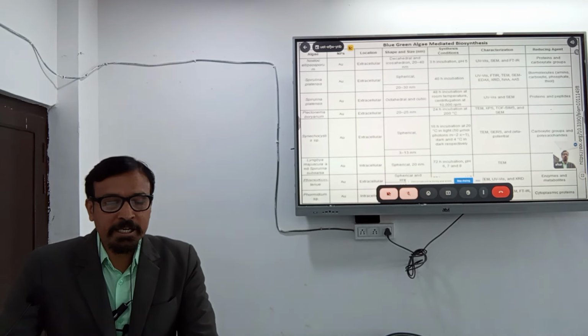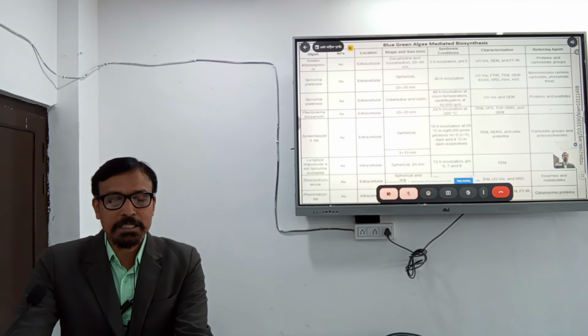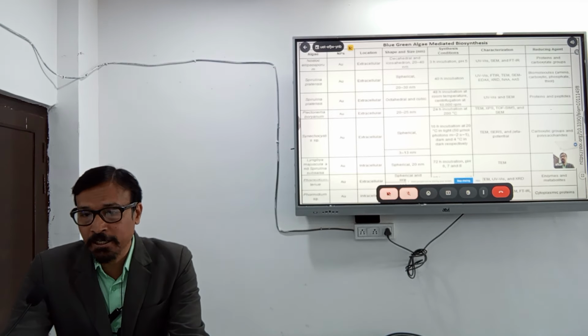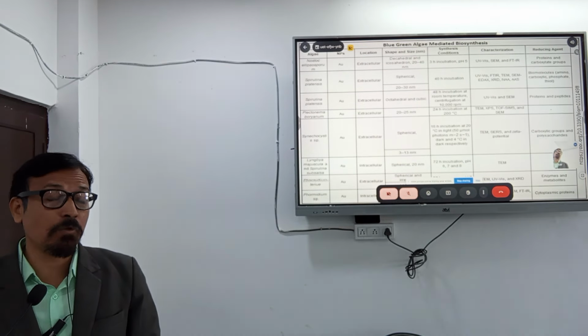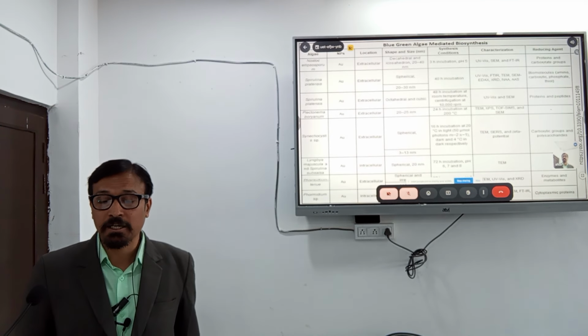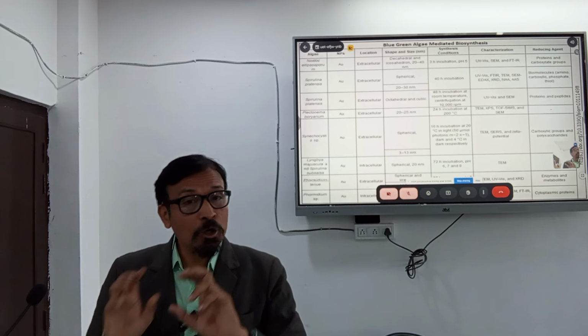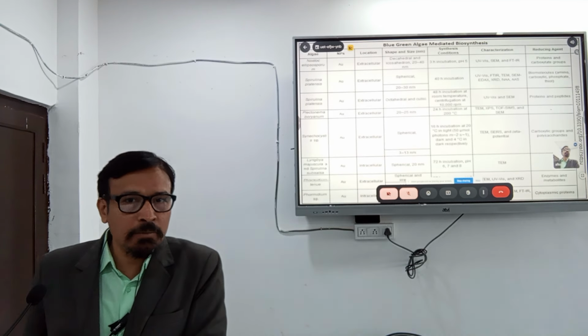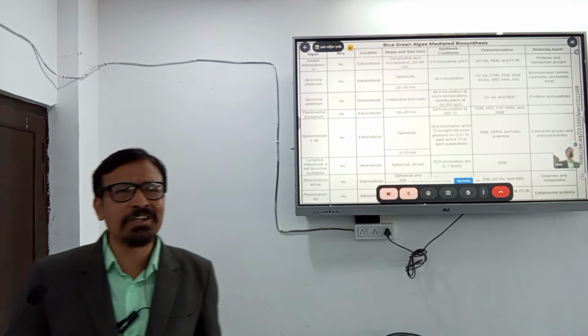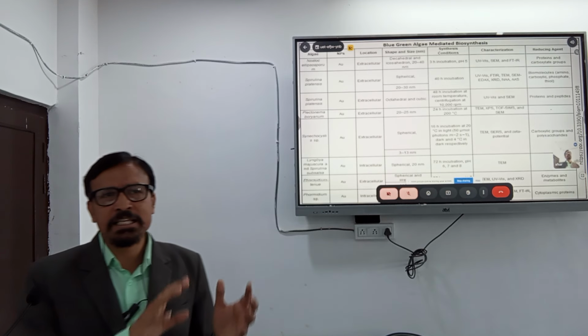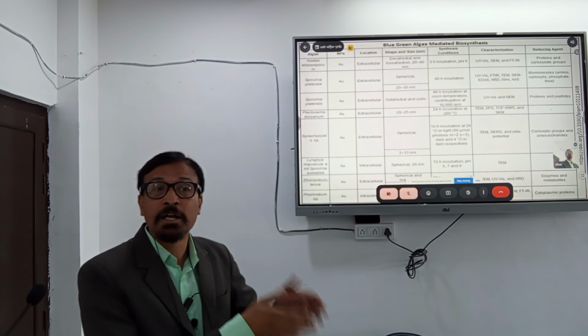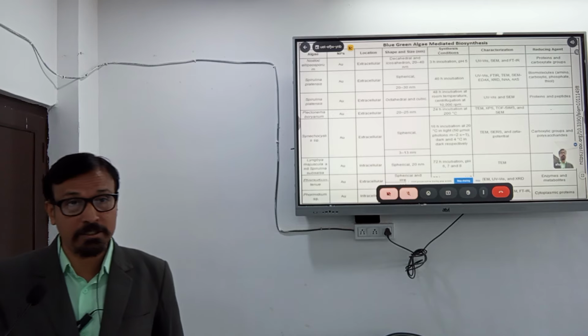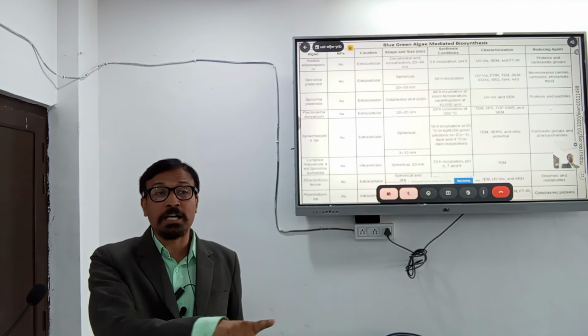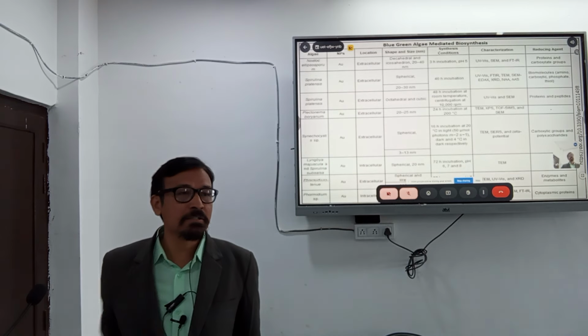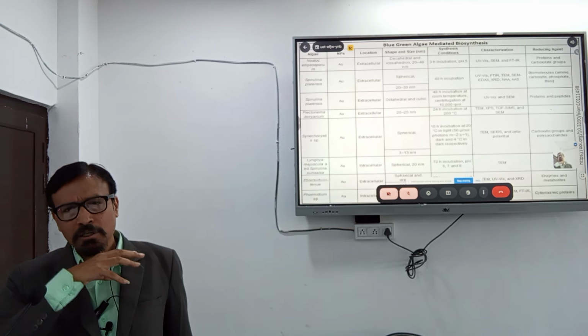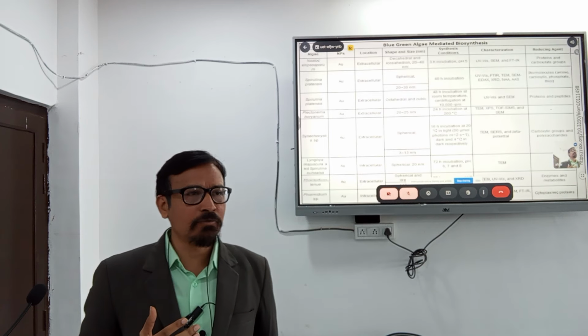Okay, so Phormidium tenue is another algae which can synthesize silver nanoparticles extracellularly. Spherical and irregular shaped nanoparticles can be produced in the range of 14 to 16 nanometers. And these are the techniques. And here the reducing agents are enzymes and metabolites. Enzymes are not usually released out of the cell; there can be conditions, but most of the time enzymes work inside the cell. So in this condition enzymes can act as reducing agents and reduce the ionic species of the metallic nanoparticles. In other cases, biomolecules, phenolics and flavonoids are also released outside of the cells.